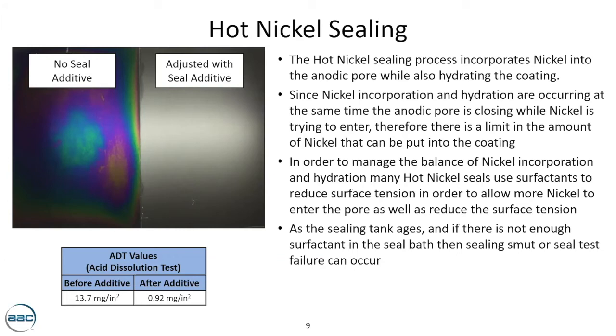If you look at the ADT values, clearly before the additive, you were at 13.7. Now that's already an improvement from what you were seeing with the hot DI in the slide earlier. So there is a benefit in just using nickel itself. You're getting some nickel into the pore at minimum, but closing and performing that hydration step is critical. And after you make the addition of the seal additive, which allows more nickel to get into the pore and allows you to fully hydrate that pore, you'll see that your ADT values are much lower.